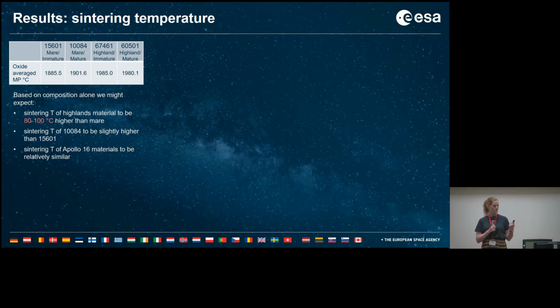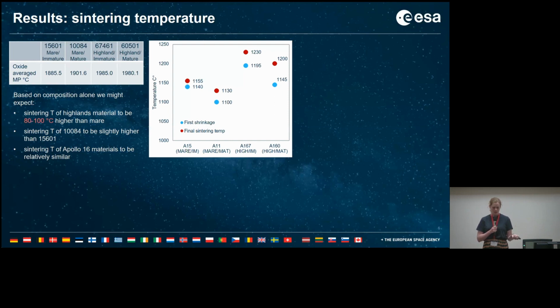And from this, we might expect that the sintering temperature of Highlands material would be about 80 to 100 degrees higher than Mare. We'd also maybe expect that the Apollo 11 material would sinter at a slightly higher temperature than Apollo 15, and that Apollo 16, because they have quite similar compositions, would sinter roughly at the same point. And so this chart shows the observed temperatures that we saw.